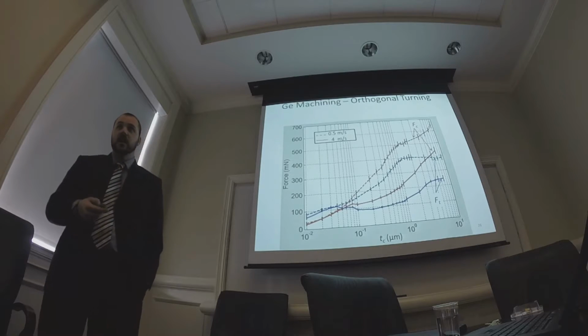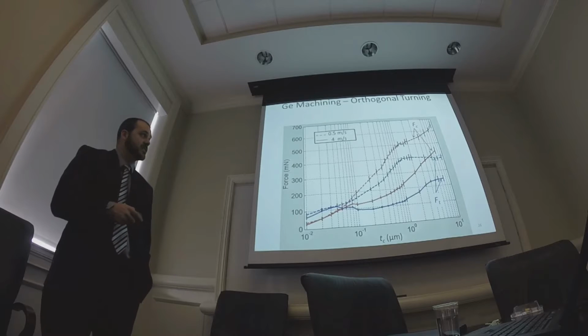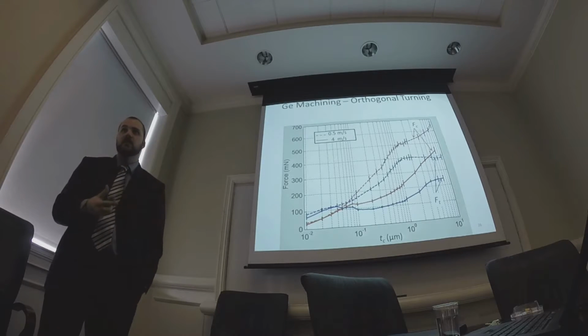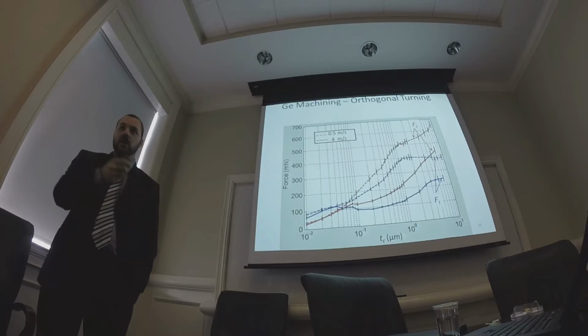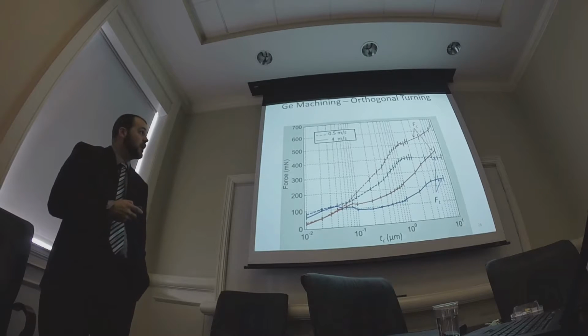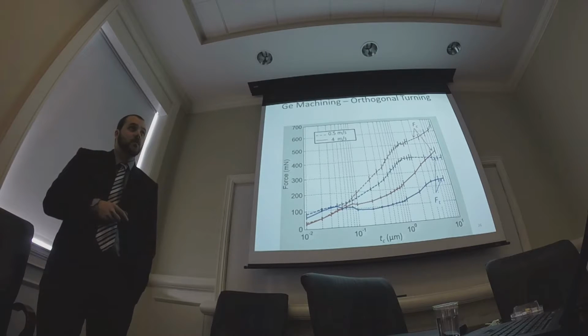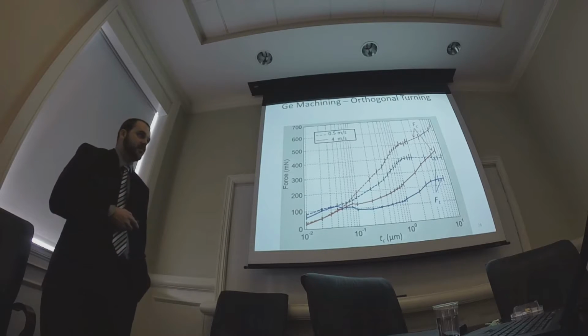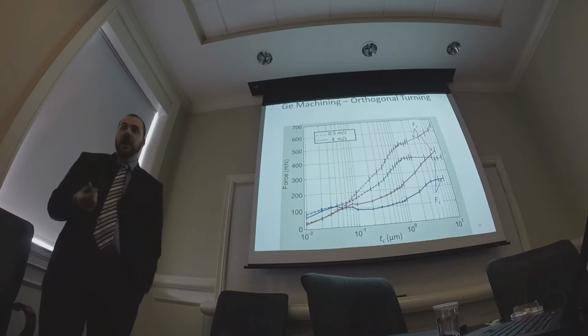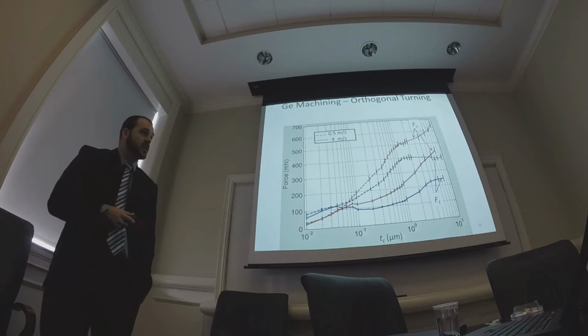We thought this was going to happen, but it was still pretty exciting to see it actually happen, because 4 meters per second is typical milling speed when you work your way up along the diamond. 4 meters per second on a 1-inch diameter part was like 4,000 RPM. So you can turn at that speed, which obviously we did, but you wouldn't always run at speeds like that.